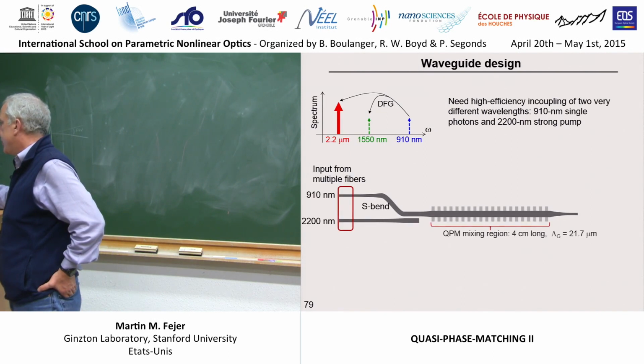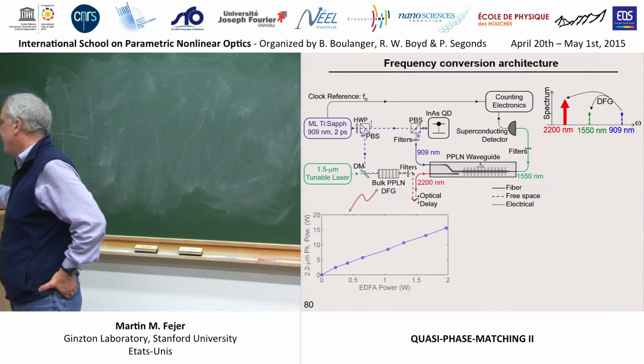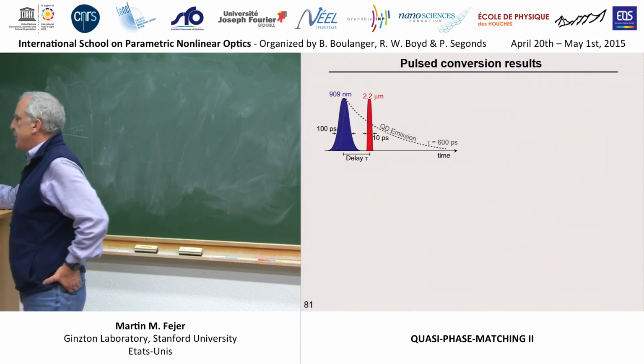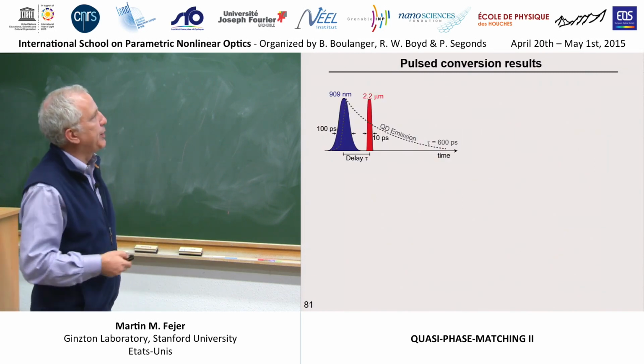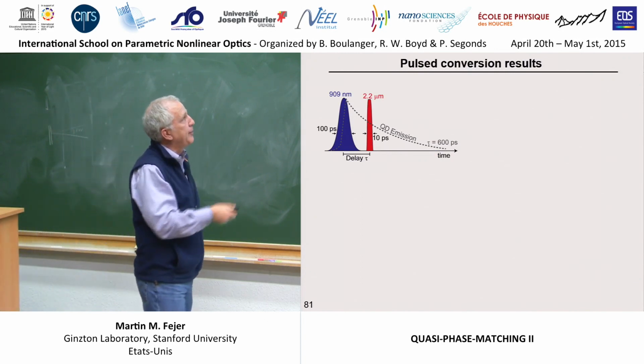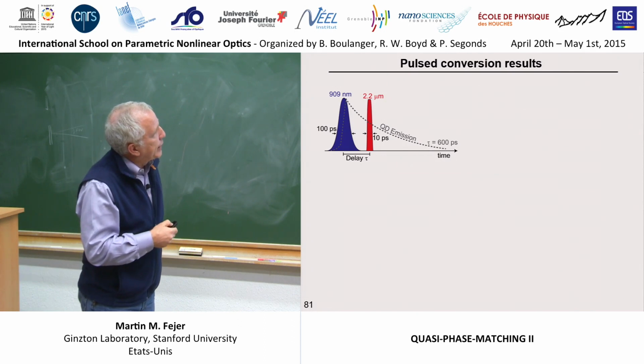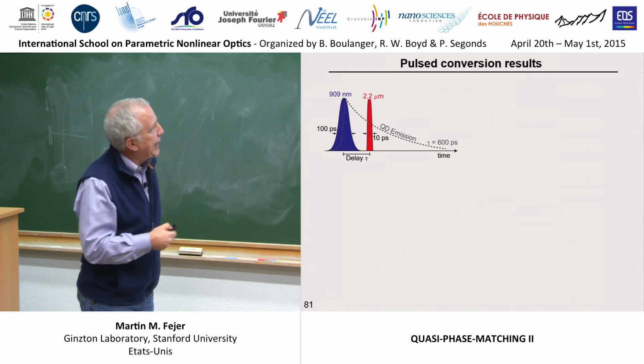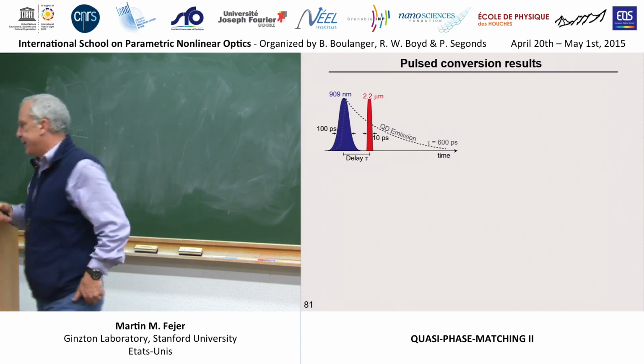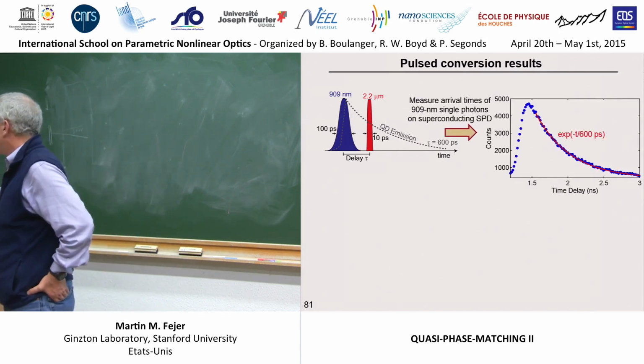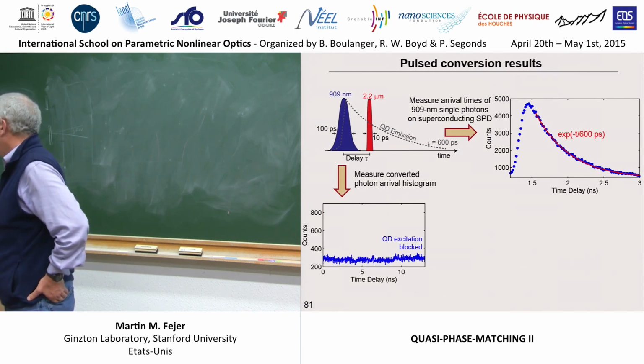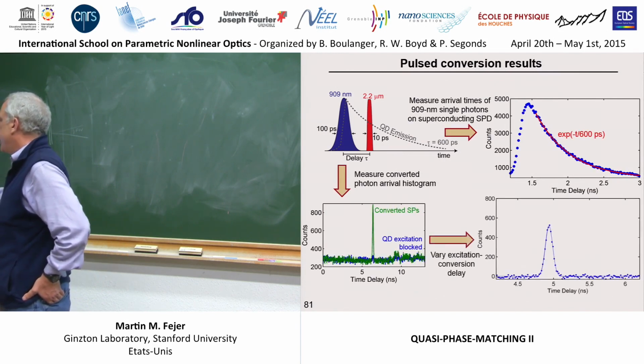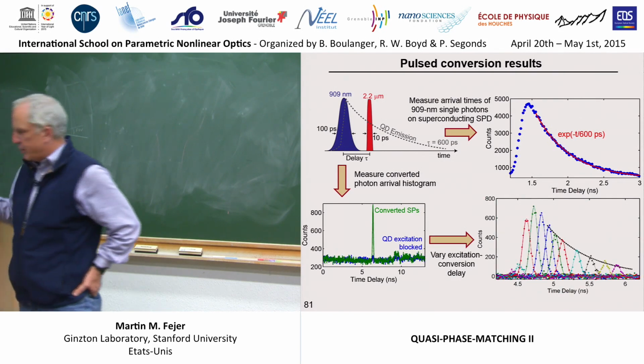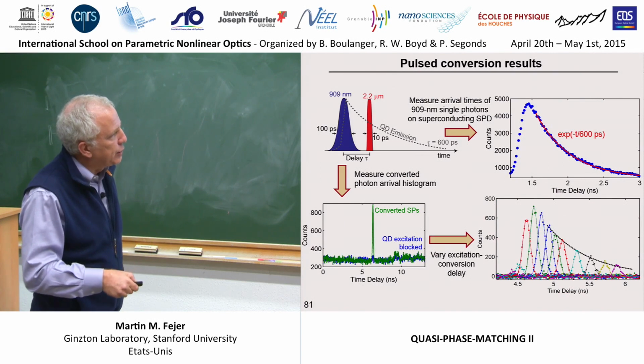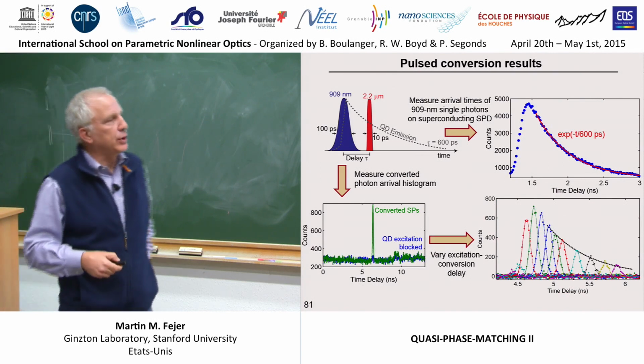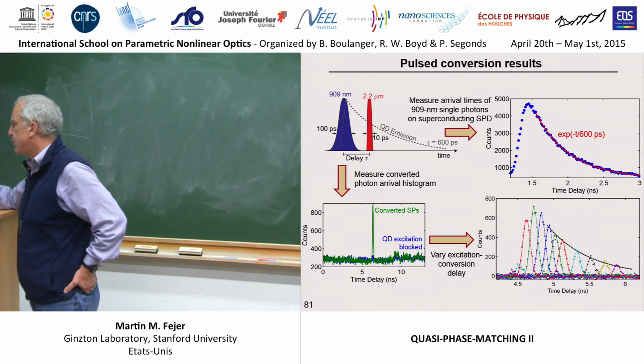In the interest of time, I won't talk too much about this experiment other than to note that it was interesting to analyze a quantum dot that had sort of a 600 picosecond spontaneous lifetime, and look at upconverting single photons with a 10 picosecond gating pulse. This was a long story as to why this was a valuable experiment for understanding the dynamics of the spin behavior in that quantum dot. But the upshot is you could trace out this behavior with roughly 10 picosecond resolution using this kind of gated down conversion process.